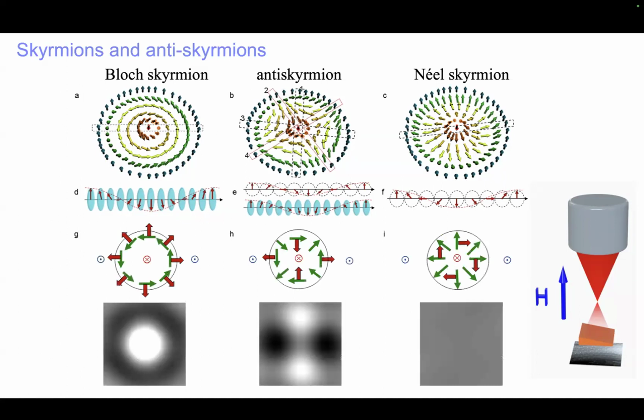And these are so-called Lorentz images of a Bloch skyrmion on the left-hand side. It turns out that the magnetization components in the plane of this Bloch skyrmion cause the electron beam passing perpendicular through it to be scattered towards the middle or to the outside. And a Néel skyrmion, because the different components of the magnetization in the plane will cause the beam to be rotated around the circumference, you cannot see anything in the Néel skyrmion.